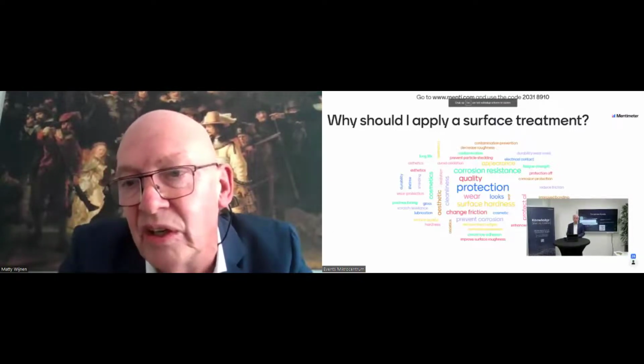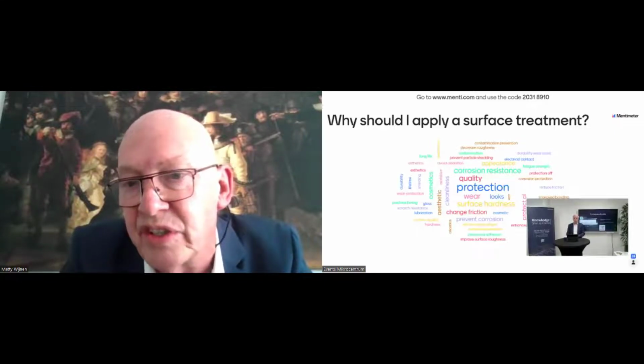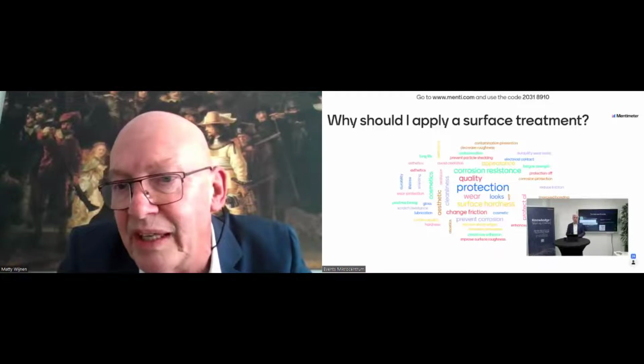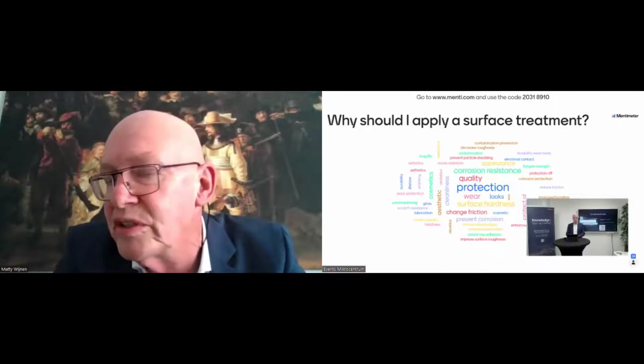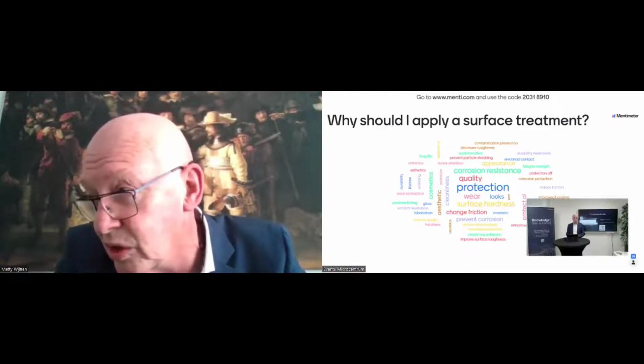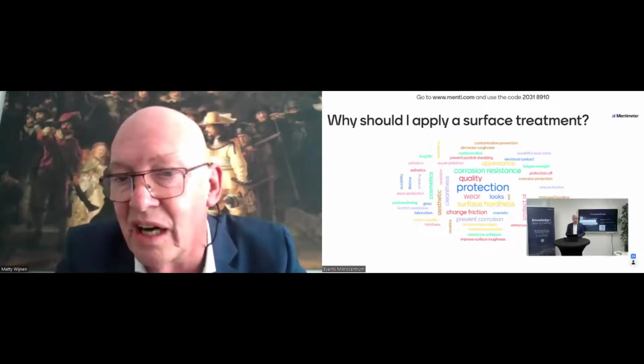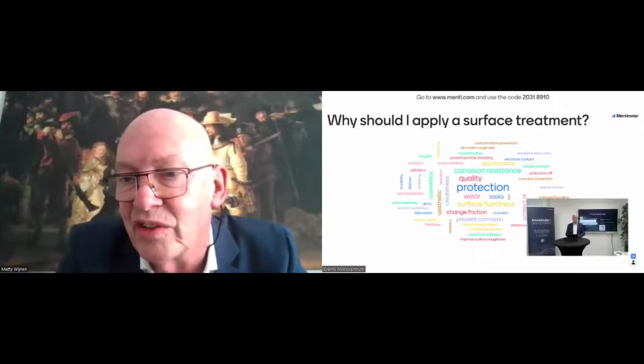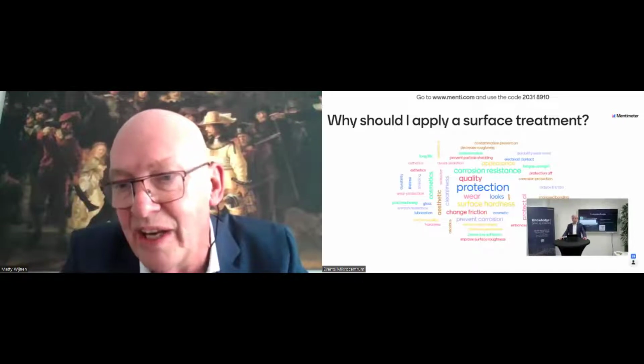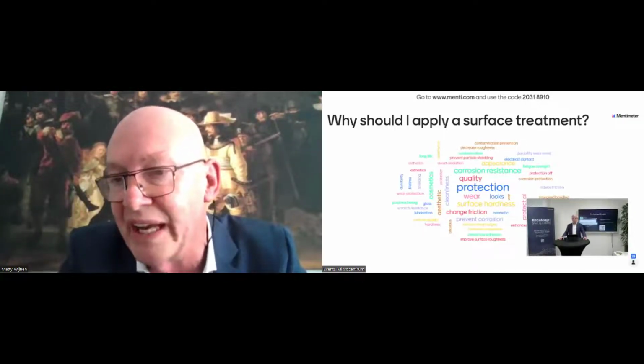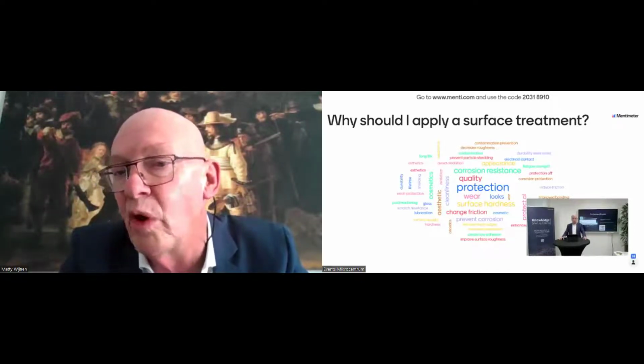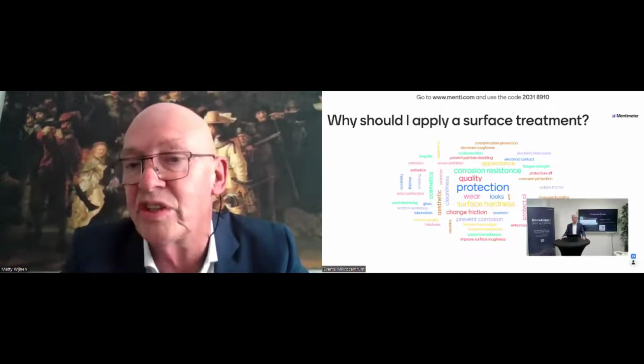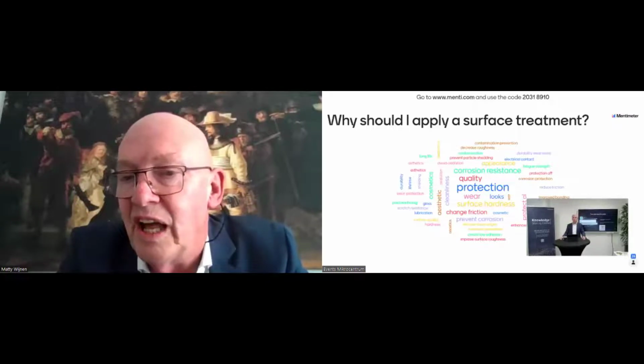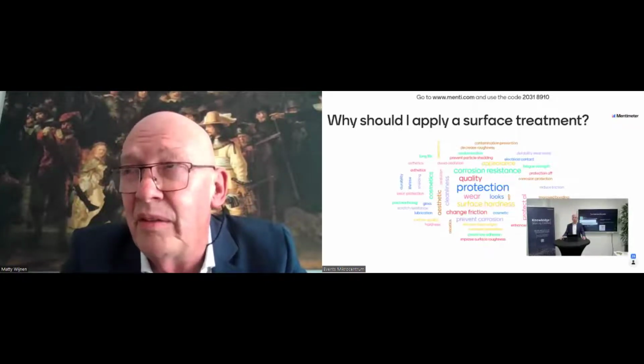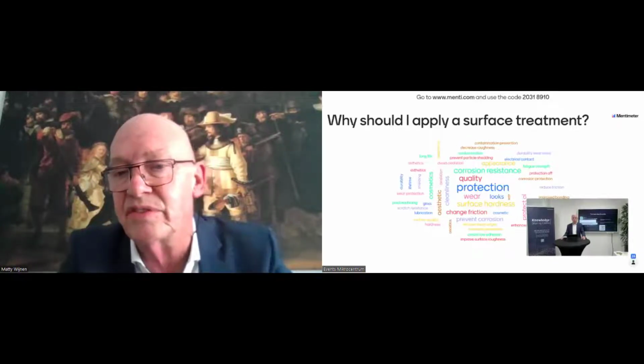So what you do mostly is you look for combinations. For instance, you say, okay, I need corrosion resistance, but perhaps I need also appearance. And what you then get is what's now known as, for instance, nickel chrome coatings. And nickel chrome coatings are coatings which are used on furniture and in the early days on cars, at least in my early days on cars. You saw those nice shiny bumpers of the cars, really bright. Now, they're nickel plated just for the corrosion resistance, very thick layers, highly bright. And then coated with a very thin chromium layer, to make sure that the nickel which is on is bright, is hard, is wear resistant, so it won't damage when you use it, and you combine those things. So there's a lot of things to do, but with the vast amount of different possible coatings, it's very difficult to say, okay, we do this and we do that.